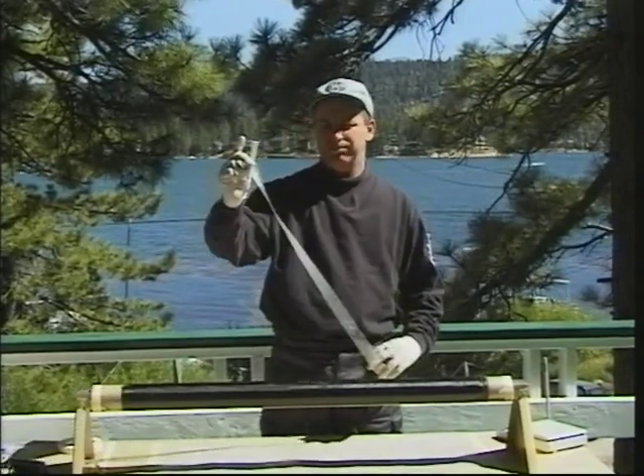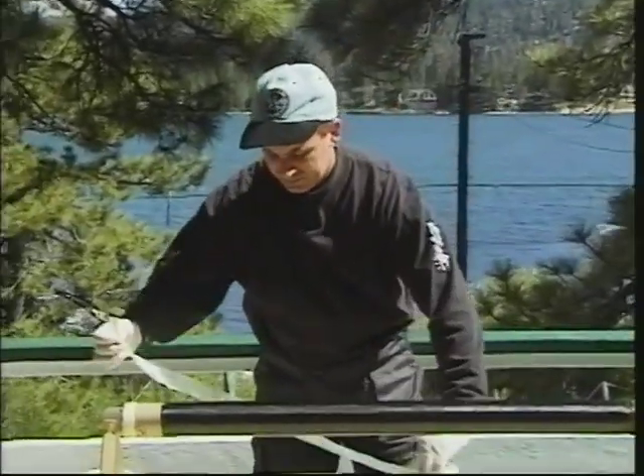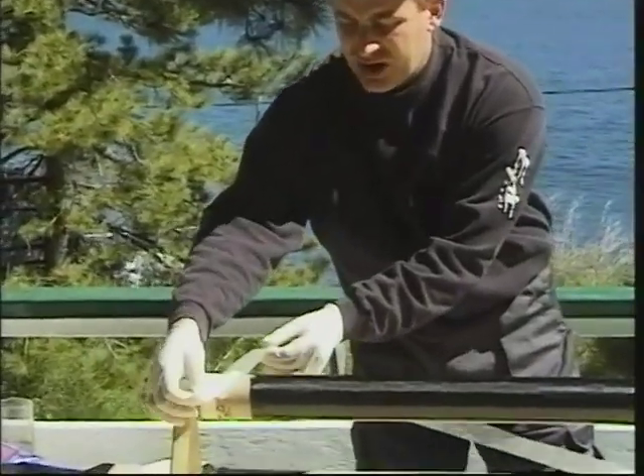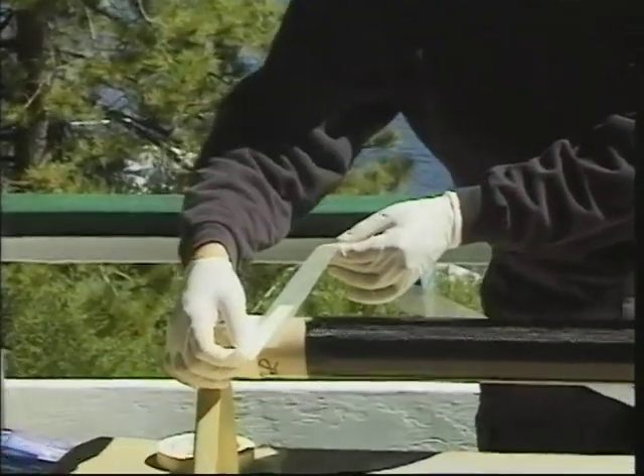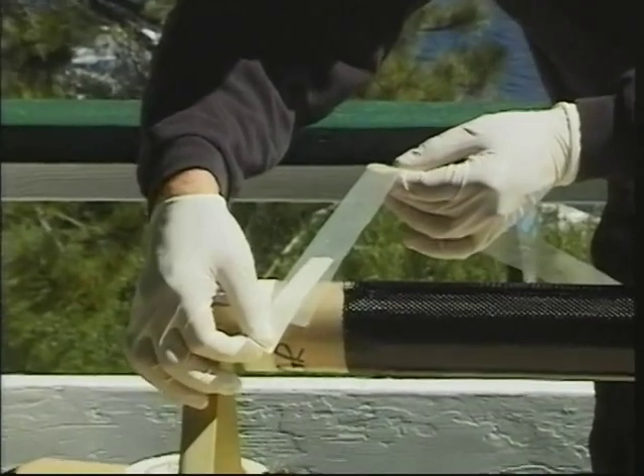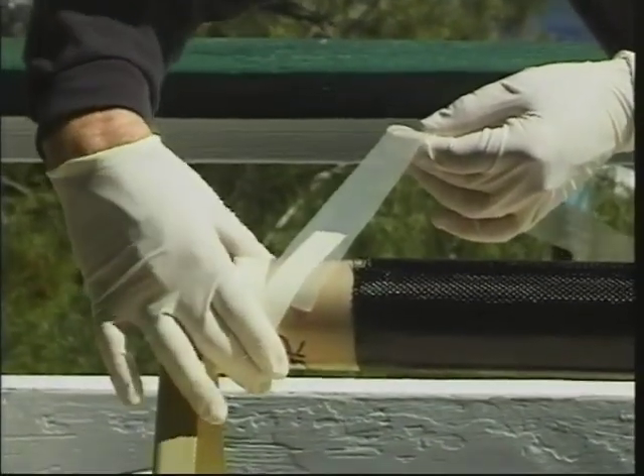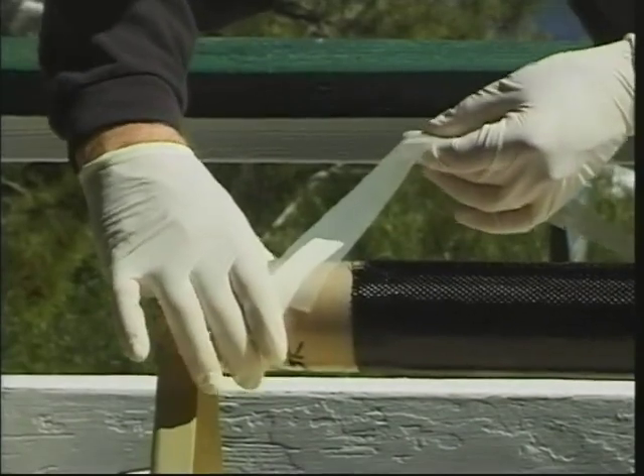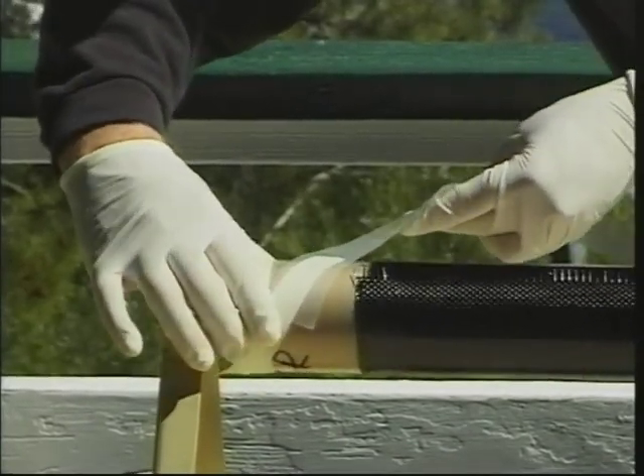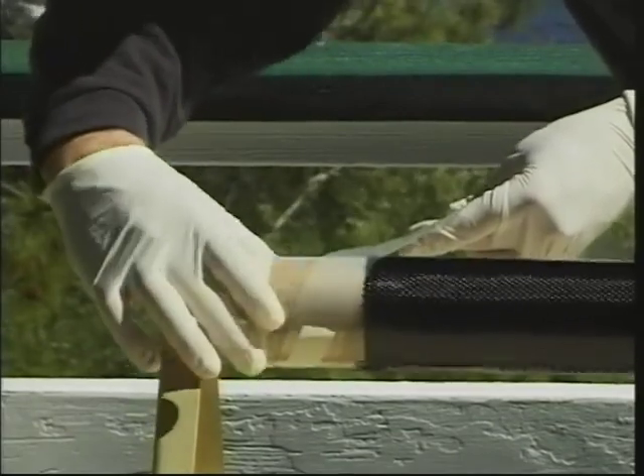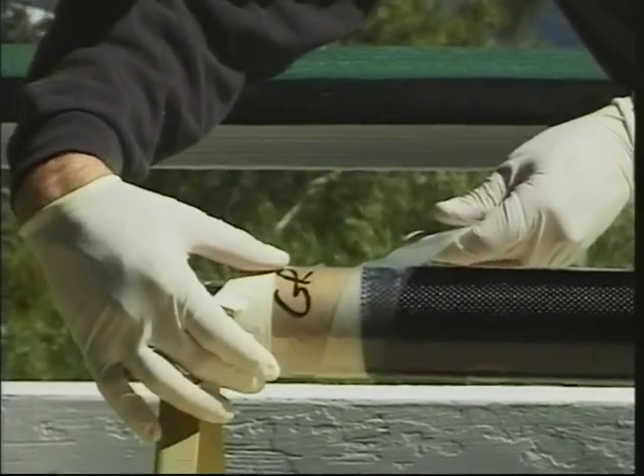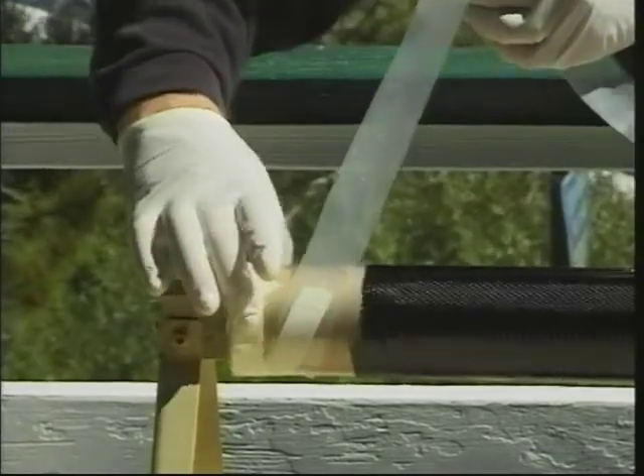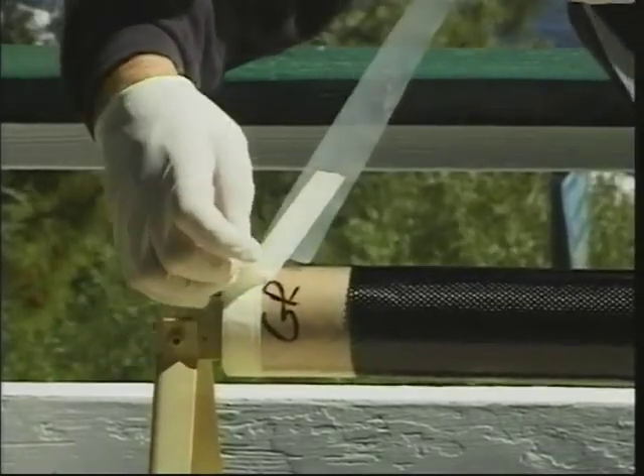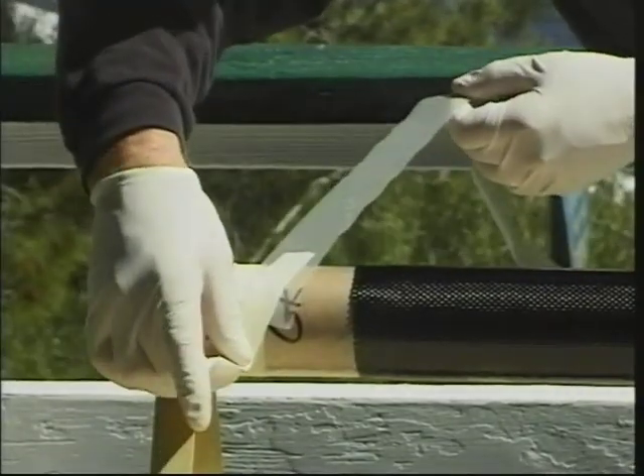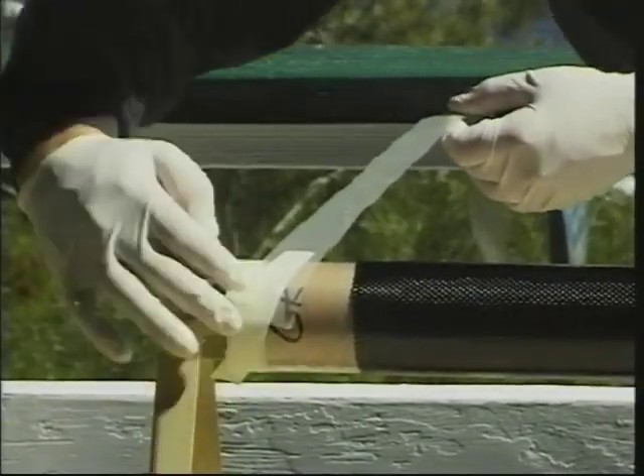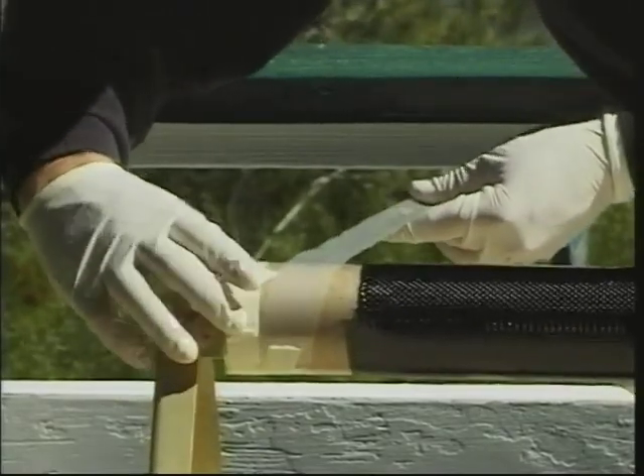is just put a piece of tape on the end of it. Now you'll see the additional reason why I've got the runoff on these tubes. If we can zoom in here, I'm just starting this tape all the way at the end of the tube, past the carbon on the coupler at a shallow angle. I'm at about 15 degrees. And now I'm going to start wrapping this around. Let me do that again just to show you how we start the tape. Get your tape on the end there, nice shallow angle, and start wrapping it around.